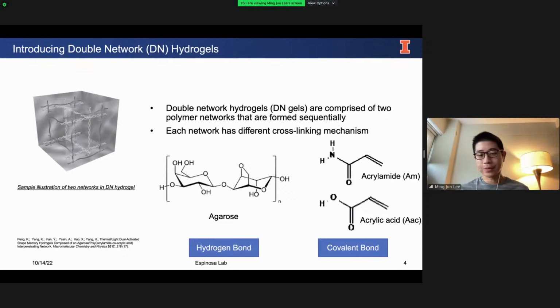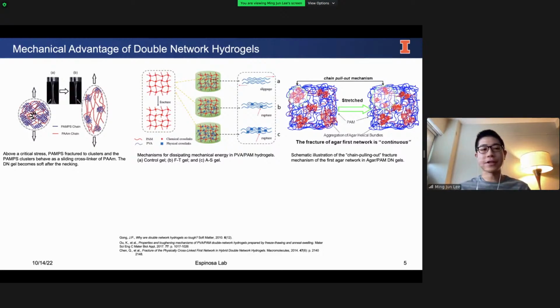My particular system comprises agarose as the first network, and then a copolymer between acrylamide and acrylic acid as the second network. As you can see, agarose has a physical interaction. It gelates through hydrogen bonding, whereas for the copolymer, it gelates through covalent bonds. So by controlling these two different interactions, I can time their sequential synthesis to make a double network hydrogel. And double network hydrogels can address one of the problems I mentioned earlier, where hydrogels need to be strong enough to sustain our body weight.